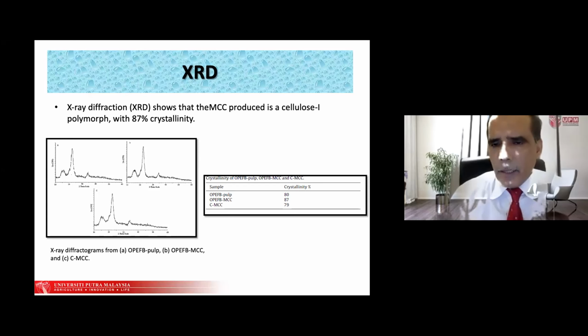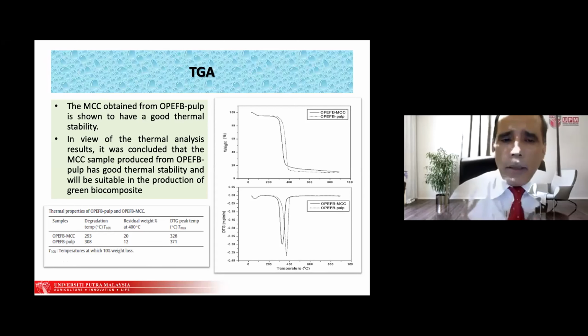And we also did the XRD, and we found that the MCC has a crystallinity of 87%. And then we also studied the thermal properties, and we looked at the degradation temperatures for the MCC, the pulp and the residual content, and the peak temperatures we are getting. In view of the thermal analysis results, we concluded that MCC samples produced from the oil palm pulp have good thermal stability, suitable for the production of green composites.